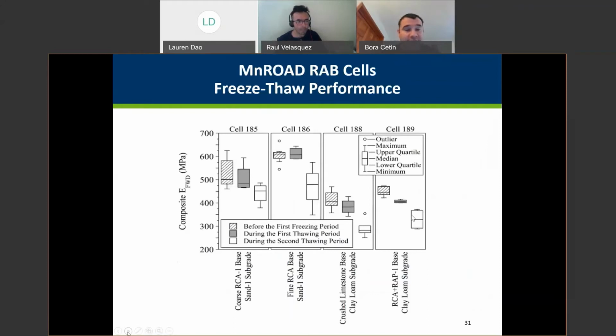And then we also look into the 2 years of performance, actually 2.5 years of performance, of these recycled base materials. On the first column, we have the coarse RCA base, the second column is fine RCA base, the third column is crushed limestone base, and the last column is RCA+RAP base. As you can see, even before the first freezing period, the fine RCA and coarse RCA base layers have much higher stiffness, from the elastic modulus collected from the FWD test before the first freezing period. And RCA+RAP had higher stiffness than the limestone materials too.